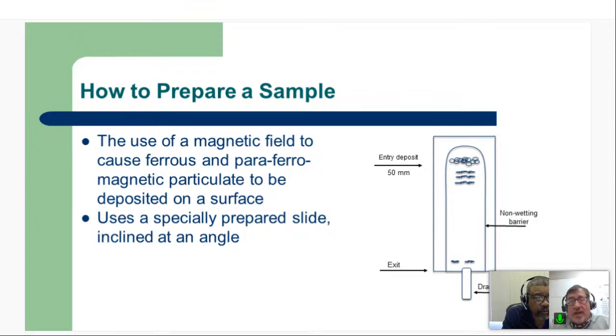Well, the slide is not just a glass slide. It has a plastic-like material painted on there. And when the solvent hits that, it softens it. So now when the magnetic force or just gravity pulls particles down to the surface of the slide, they get embedded into that matrix. And then when things evaporate and dry out, they're held in place. They're fixed. In fact, we used to call the solvent a fixer, because it first softens and then evaporates and hardens again, fixing the particles on the slide. Otherwise you would take this off of there and you would sneeze and you would lose all those particles, right? So this is the way that we capture them in this specific arrangement.